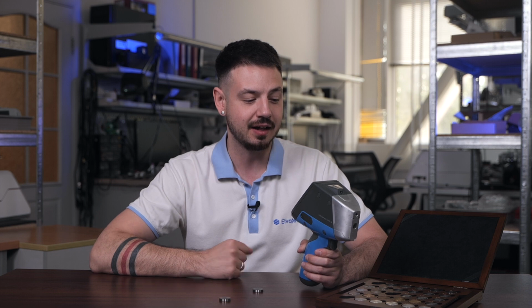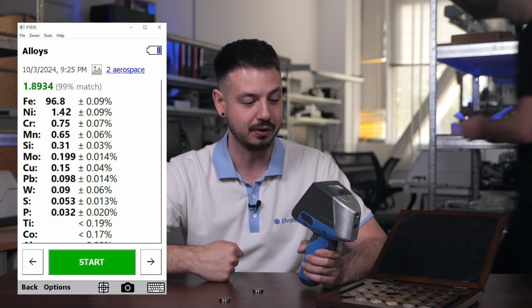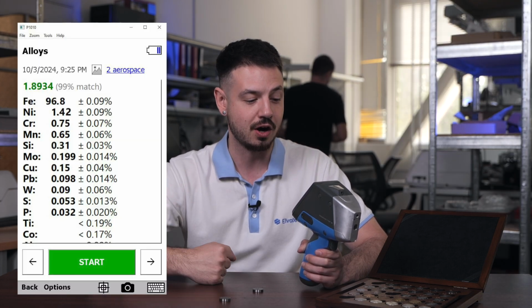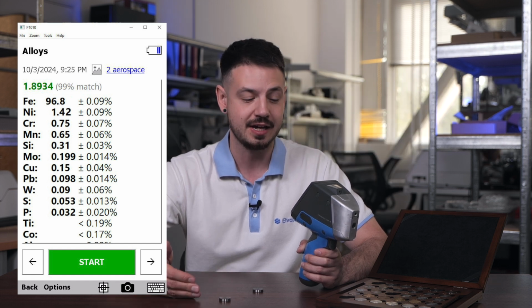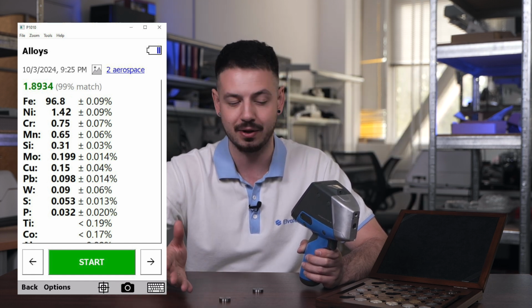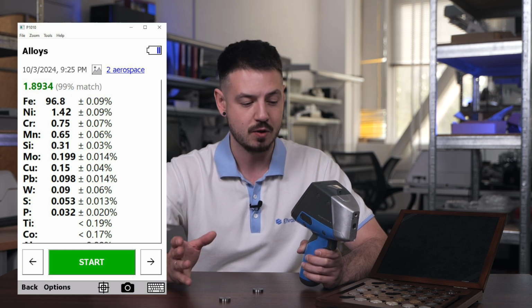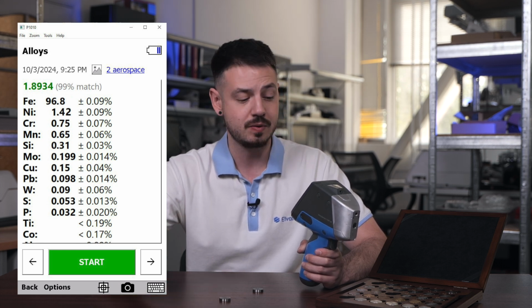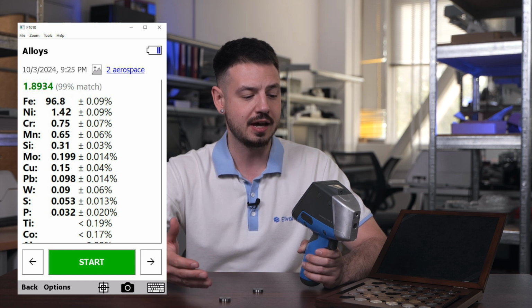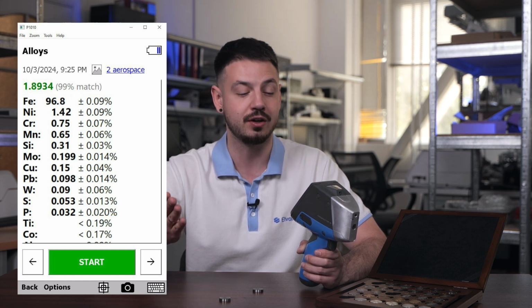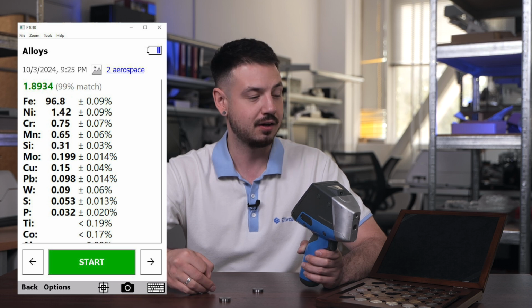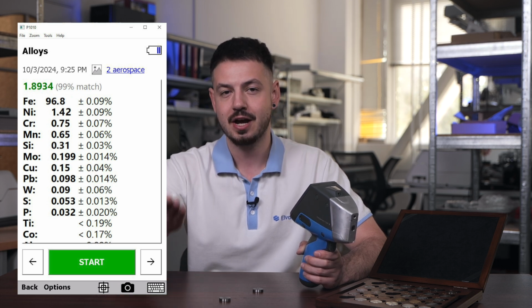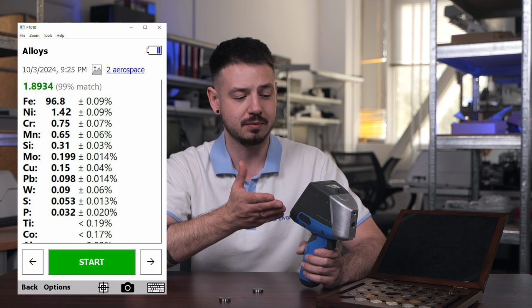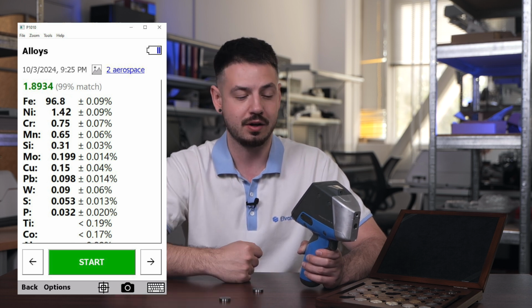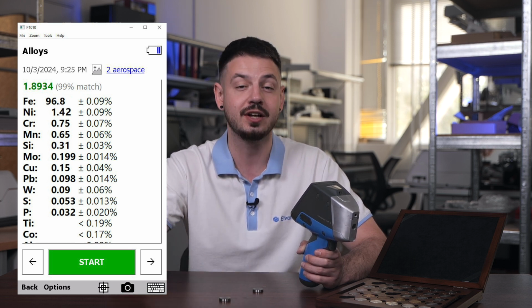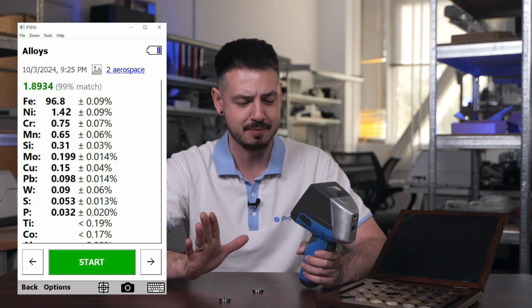So the leading element, the base element of this sample, is actually ferrum in a concentration of 96.8, and the appropriate concentration for this sample is 96.2 ferrum. Also, we have nickel, which has a concentration of 1.42, so almost 1.5%. The averaging position for it is 1.4. So here we are absolutely good too.